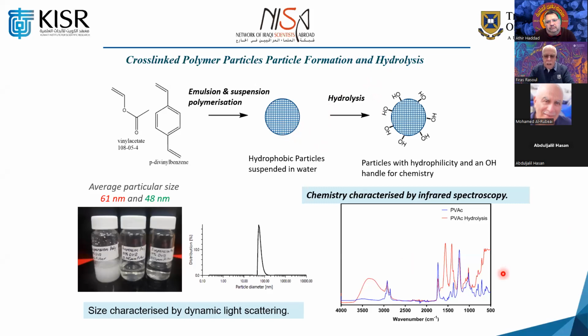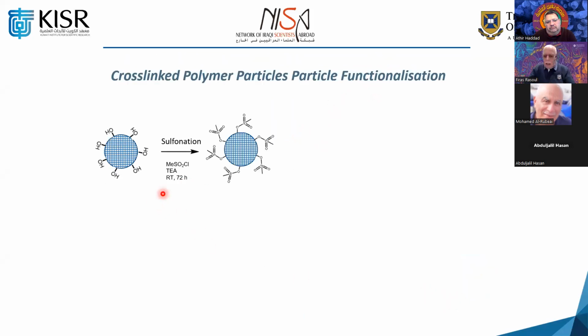Yeah, so this is the characterization for that. Again, what did we do with that after we hydrolyze it? We sulfonated it, putting that sulfonated group. It is pretty straightforward chemistry. It is a little bit slow at room temperature, 72 hours. And then we converted that sulfonate to azide, reacting it with sodium azide at 80 degrees centigrade for 48 hours.